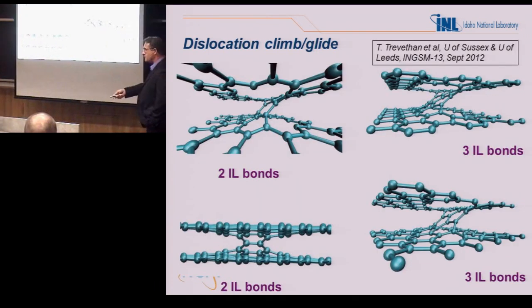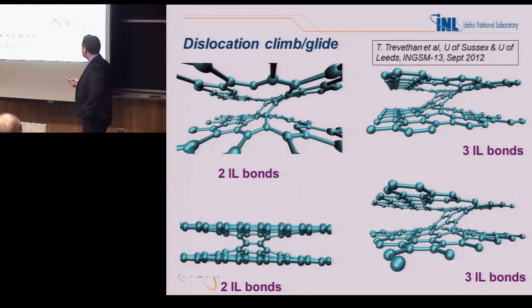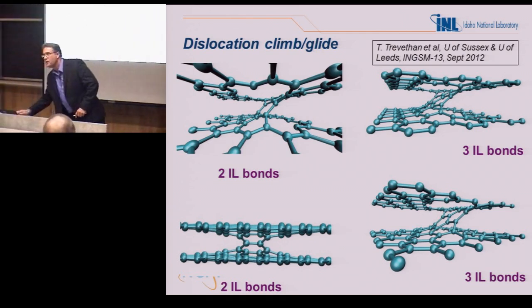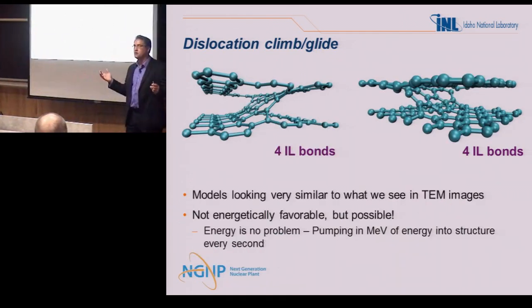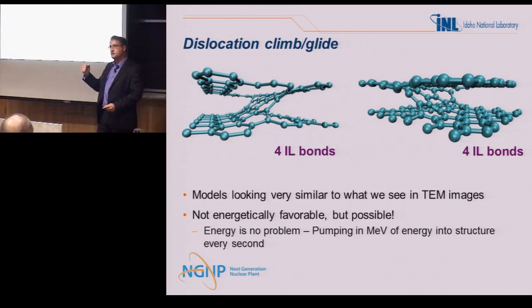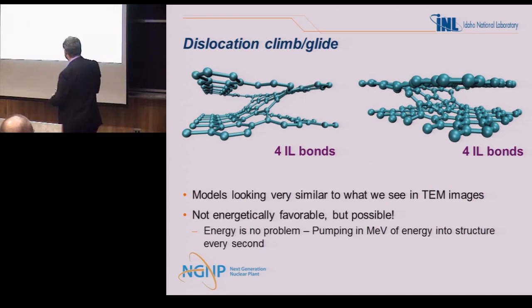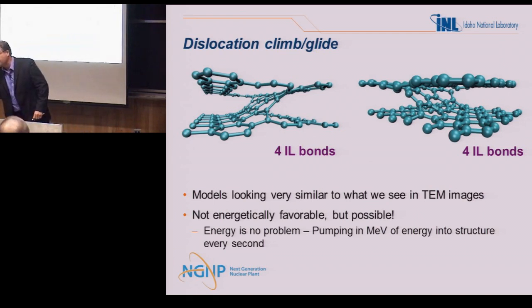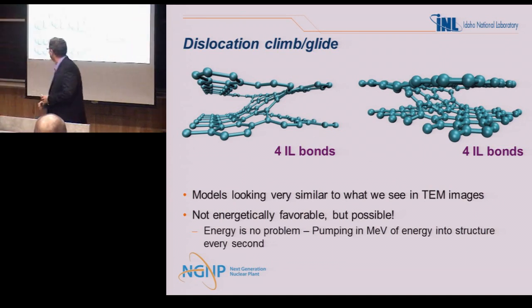This is some models after we produced those basal plane interactions. This is some models that the University of Sussex back in the UK came up with, where they showed that, yeah, it's not energetically possible, but it can be done, where you actually have some bridging between the basal planes. Not very energetic, but when you're talking about million electron volts of energy smacking into these things from a neutron, anything's possible. Okay? So the models look pretty similar to what we see in the TEM images. And again, it's energetically not very favorable, but it is possible.